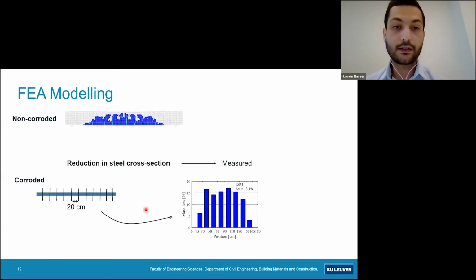The reduction of the steel cross-section was measured by extracting the steel from the concrete after the bending test and cutting it into pieces of 20 centimeters. In this way, I can obtain the variation in the cross-section loss, and I can also obtain the average cross-section loss of the full rebar.